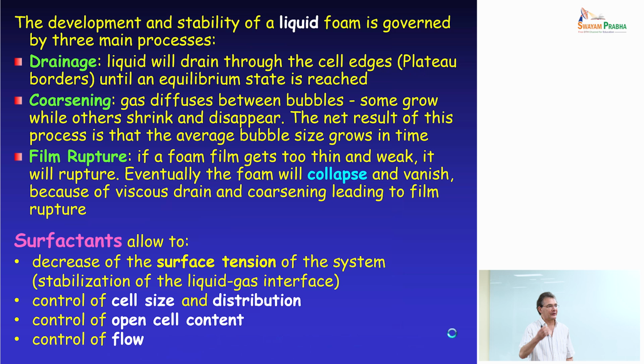After you make the foam, you have drainage. The liquid will drain through the cell edges until you reach an equilibrium state. You have coarsening, where the small bubbles tend to disappear and the large bubbles become larger and larger. And then you have the collapse of the foam due to liquid film rupture.